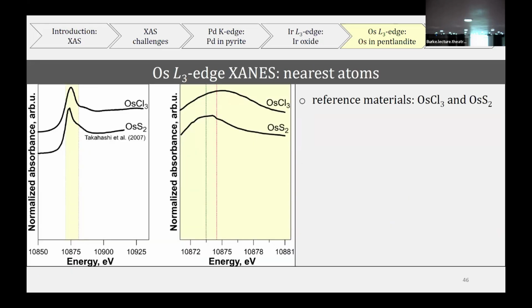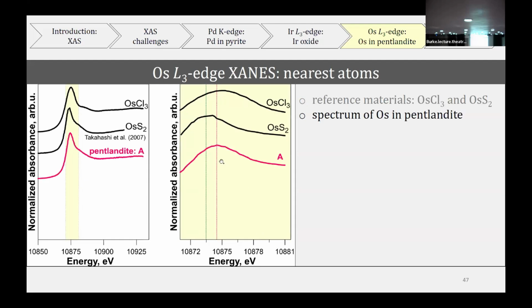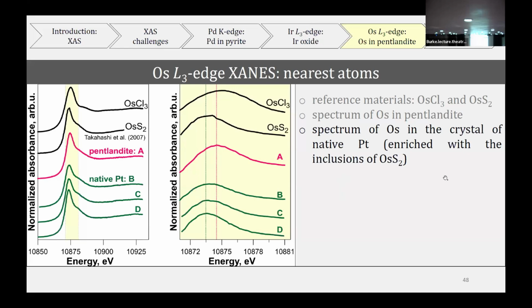So in order to prove or disprove these statements, we performed XAS again, and these are the reference materials and the spectrum of osmium in pentlandite. I know that in this picture they look quite similar, but it's not quite like this. If we look at the enlarged portion of this region, we see the differences. Our osmium in pentlandite is very different from OsS2. We also compared it to a few other standards, which are not quite standards, it's also a sample, but we suspected that this native platinum was enriched with OsS2 inclusions, and that appeared to be true. But now we can compare with the OsS2 recorded in our experiment, not from the literature like this one.